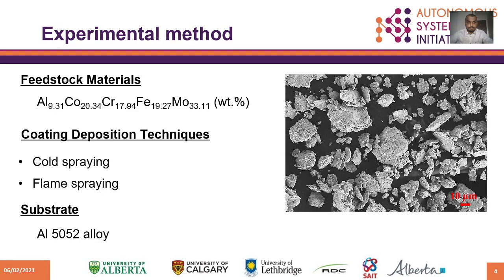The HEA feedstock in weight percentage is shown here, and the micrograph shows that the particles are agglomerated with an average particle size around 15 micrometers. Two deposition techniques will be utilized. One is the cold spray technique, where small unmelted particles are accelerated at high velocity to impact the substrate, and it has a low temperature heat source.